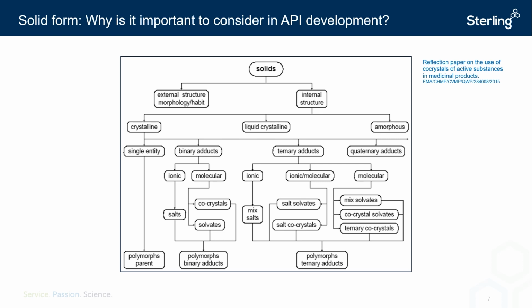For instance, the external appearance, that is, particle shape, can influence the isolation of the API and the bulk powder properties, while an amorphous solid, which would have high solubility, might have a poor shelf life. Alternatively, we might have a crystalline solid with a low melting point that is not suitable for downstream processing. An alternative arrangement of the API might offer a different polymorph or version, such as a salt or hydrate, which could improve these characteristics on subsequent processing.